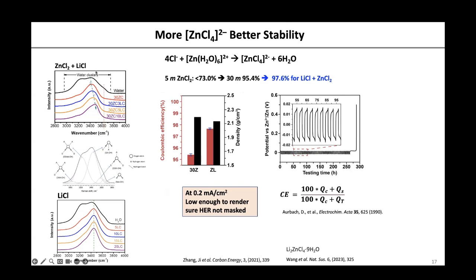We found that this peak is shifting to a higher frequency, it's blue shifted. Now, if you look at the water stretching vibration modes, the left side is heavily hydrogen bonded, and the right-hand side is not so hydrogen bonded. And usually, a higher frequency means a better stability. The water molecules' OH bond is vibrating faster, and that means the bond length is shorter, and the bond enthalpy is higher.